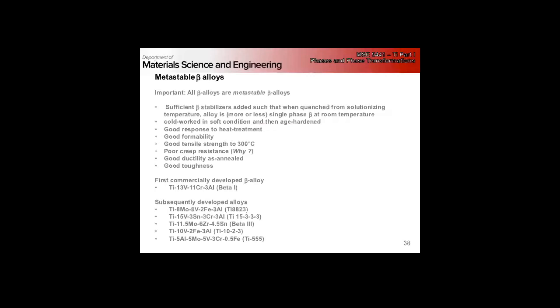If we look at the metastable phase diagram, we will eventually get to other stuff, right? Beta phase: good formability, reasonable tensile strengths, poor creep resistance. Why? Why was the alpha beta so much better in creep? Right. Complex microstructure, low diffusion in alpha. So for both dislocation creep and diffusion creep, you had better resistance, and better as annealed, much better toughness.